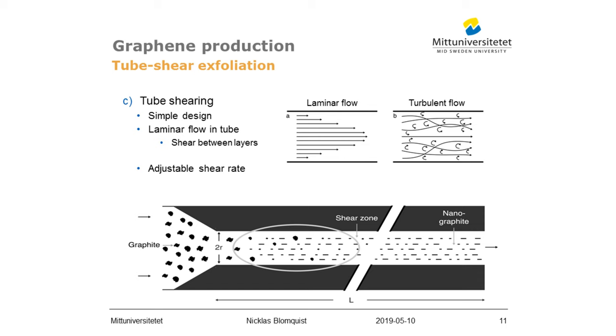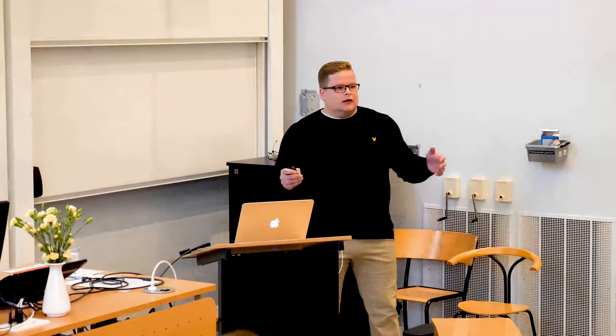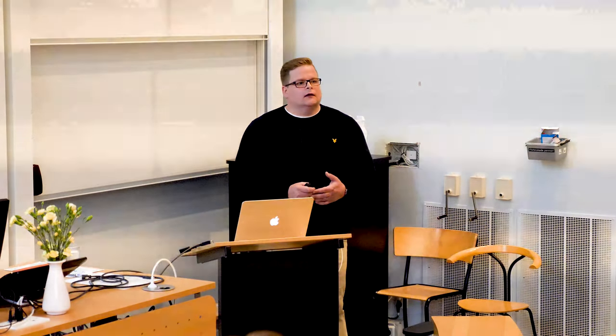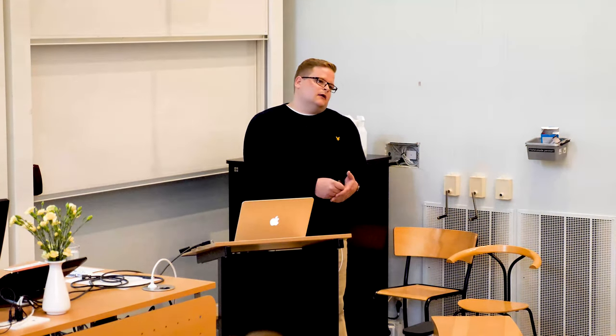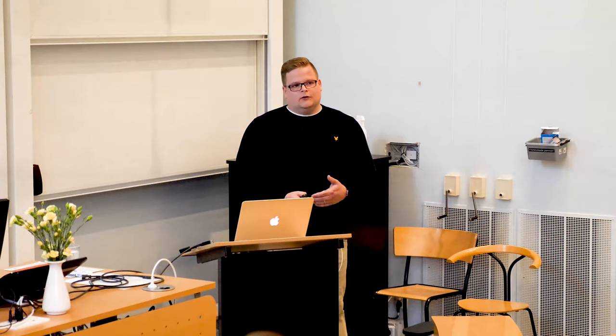This tube shear system had a very simple design and adjustable shear rate. And to prove the concept of this shear zone, we made a 1 meter long stainless steel tube with a diameter of 2 millimeters. We mixed 100 liters of water with 2% graphite and 0.04% polyacrylic acid as a dispersant, to avoid flotation and foaming when we mixed it. The flow rate was about 5 liters per minute, which generated a shear rate of 10^5 reciprocal seconds. And this is about one order of magnitude higher than the shear rate needed to exfoliate graphite to graphene with a rotary dispersion in organic solvent.